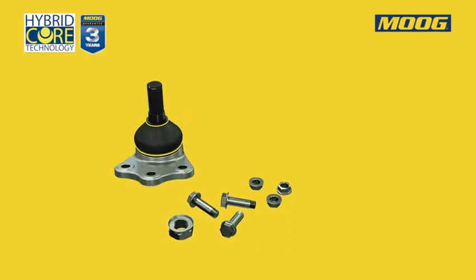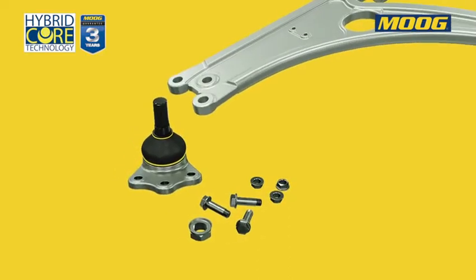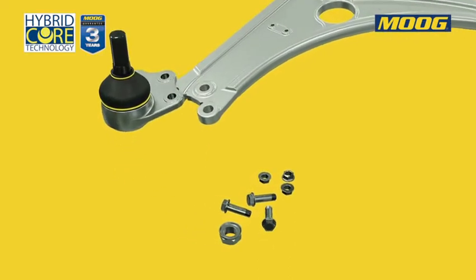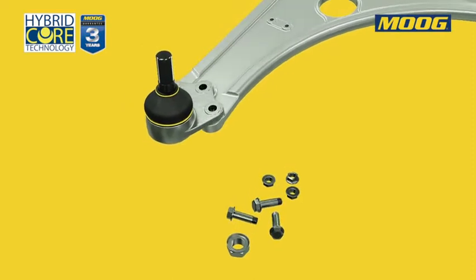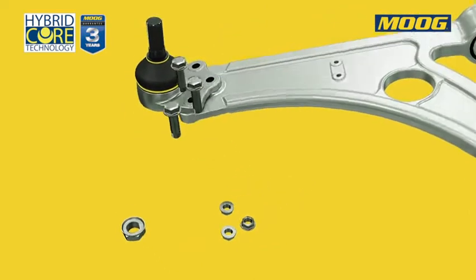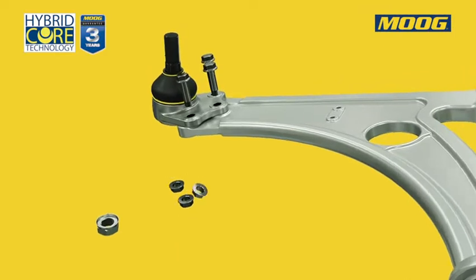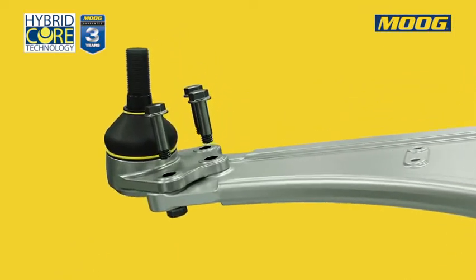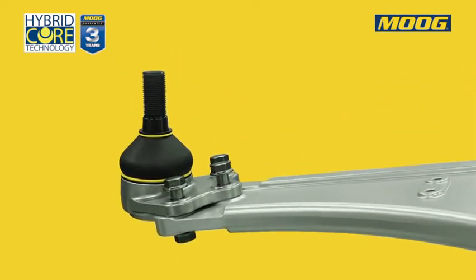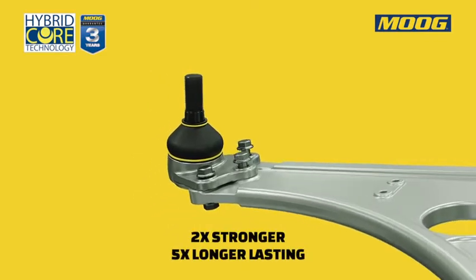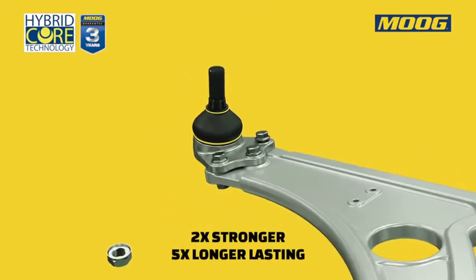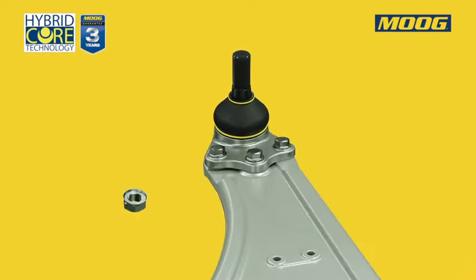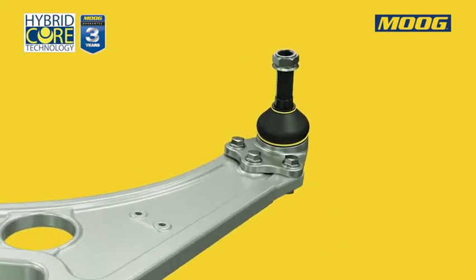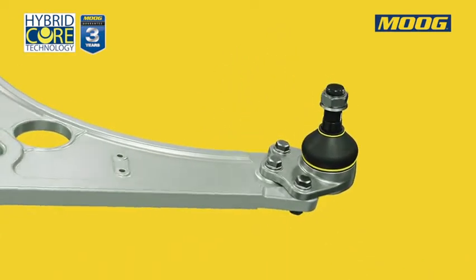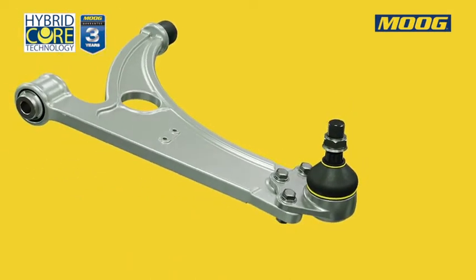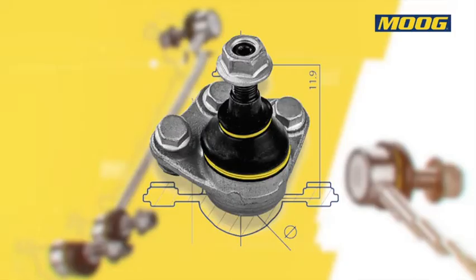Another important factor is the need to use quality fixation nuts. Flanged and zinc flake coated nuts provided by the new MOOG Differentiation range provide up to 3 times more corrosion resistance than the standard hot-dip galvanized coating, allowing a greater contact area by having a controlled friction coefficient. This feature makes it possible to adjust the tightening torque precisely, thus ensuring greater safety in the correct operation of the steering and suspension assembly.